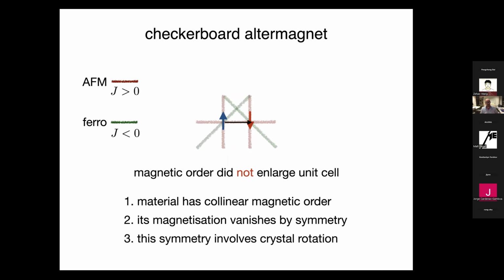So this makes the band structure very different. Let me note a few things, or let's recapitulate. First of all, I want to note that the magnetic order in this case did not enlarge the unit cell. Already without magnetic order, I had two sites in my unit cell because of the different interactions on these two sites, the different directions of the diagonal interactions on those two sites.